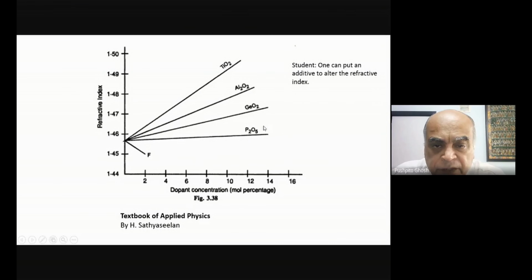Germanium, phosphorus, aluminium, titanium. All of them actually raise the refractive index. So there is knowledge that had existed in how to really change the refractive index of glass, and also how you change it as a function of the concentration, not just the type of element, but also its concentration. The only exception in this plot is fluorine, which actually tends to lower the refractive index. So that's also very interesting.